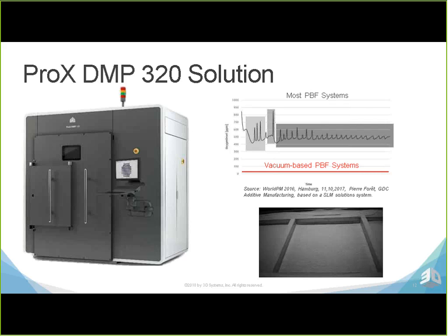There's a video on the bottom that will get running for the post edit here so that everyone can see. What you'll see is with the 320 system, using that vacuum, we've essentially developed a method to scrub humidity and oxygen out of our powder at the beginning of each build, allowing us to not have to worry about the long-term chemistry of the powder.